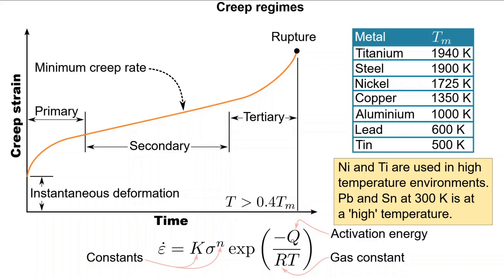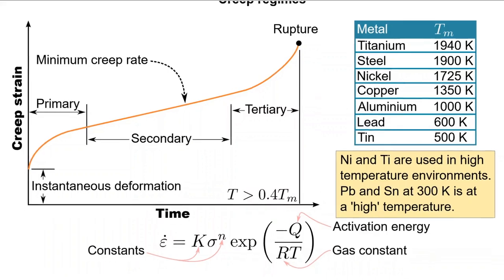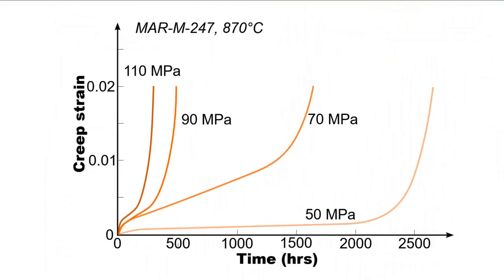Let's see how with a genuine material system that is employed for conditions that nominally see very high temperatures. Here are realistic creep curves for MAR M247, a nickel-based superalloy that's employed in stationary gas turbines. At 870 degrees Celsius the creep behavior is observed to change dramatically.